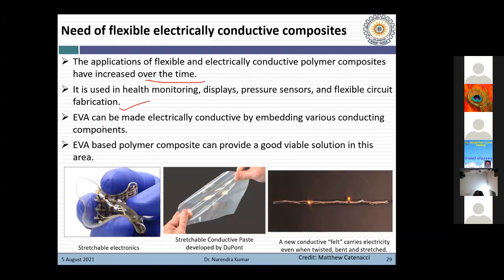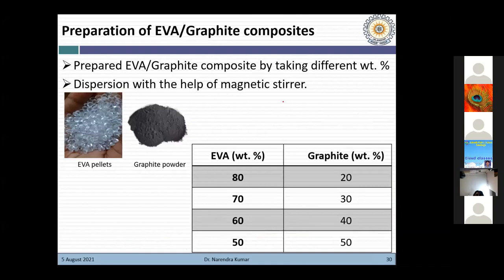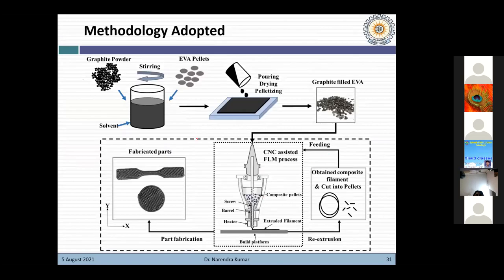As we have explored EVA, it can be made electrically conductive by embedding various conductive components. Conductive particles may be added in order to make it conductive. We use graphite as the reinforcement, or filler, particle. These are the EVA pellets, and this is the graphite powder. Different weight percentages of these two materials were taken for the fabrication, and this is the methodology we have adopted for the composite preparation.